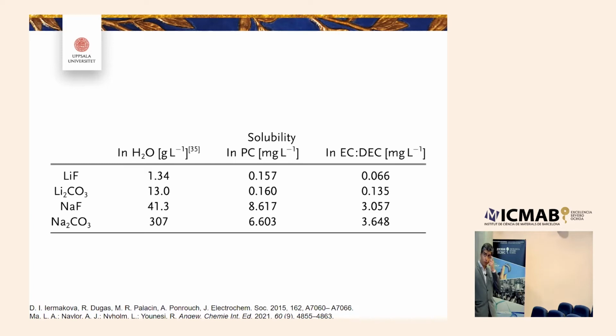Then we followed this work and measured the solubility in organic solvents. What we could learn is that the solubility is of course much lower compared to water, but there are also differences—it's not that if you go organic, the solubility is the same. There are big differences between PC and EC:DEC if you look at the solubility of these species.